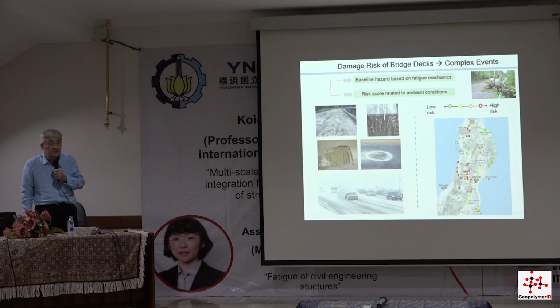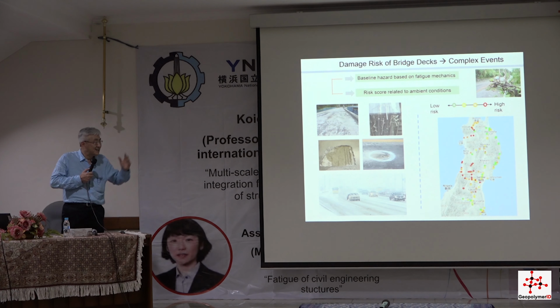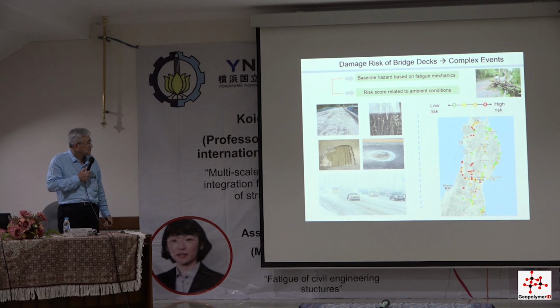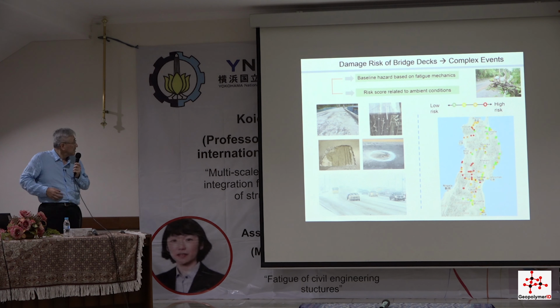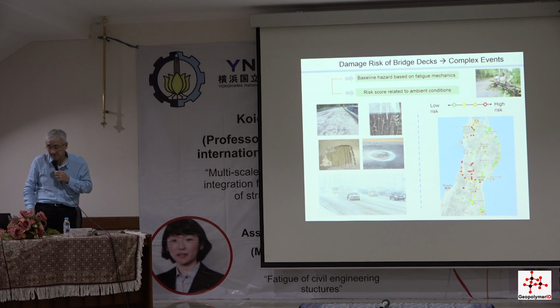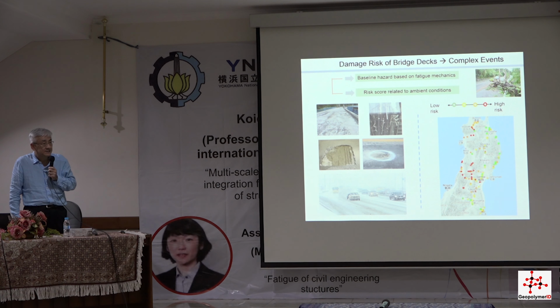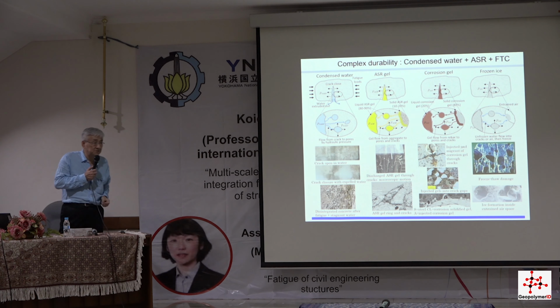But anyway, this is not the end of the story. Concrete structures are exposed to the natural environment. In the case of Japan, in the northern part of Japan, it's very cold weather. There is snowfall, sometimes freezing and thawing, and sometimes de-icing salt is sprayed on the decks, so corrosion of reinforcing bars is accelerated. Therefore, we also have to say something. But multi-scale modeling can combine the knowledge of the corrosion around the reinforcing bars. So some corrosion may create some cracking.